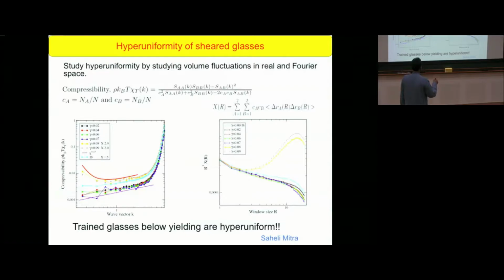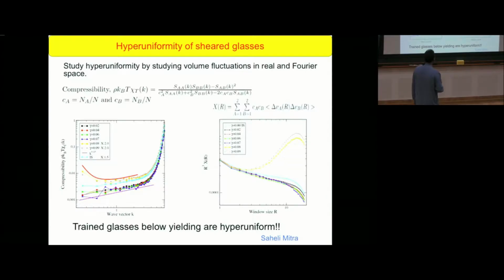Okay, this is another way of representing this using number fluctuations. There is a size of the region cubed, I've multiplied it, and these are density fluctuations. So anyway, if it was flat, it was normal. You see that in the below yield region, it's going down. So that indicates hyperuniformity. And above, by this measure, you see it getting back to normalcy. But in the range that we study, you don't see that flat regime necessarily, okay?